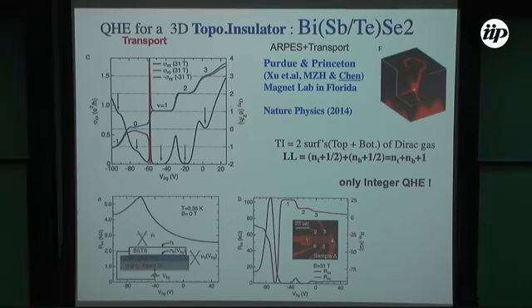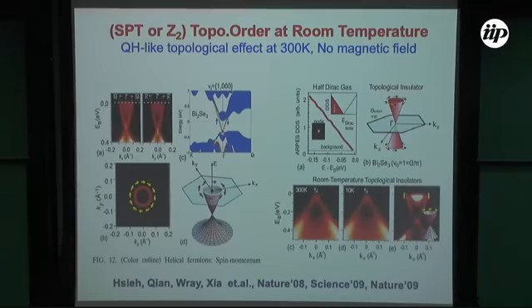But this also highlights why transport is not immediately telling you whether you are working with a topological insulator surface or with a conventional 2D electron system. There are finer checks, but then it gets more complicated. But for my purposes, what it is telling us is that we're combining that with spectroscopy. We see that on the surface, we have a single Dirac cone. We can count the number of degrees of freedom, and all these numbers match up. So the primary evidence for the topological nature of the surface state is coming from spectroscopy. You can also do more complicated transport to make a distinction. People are still trying to do much of that.